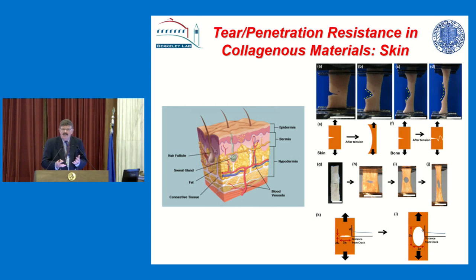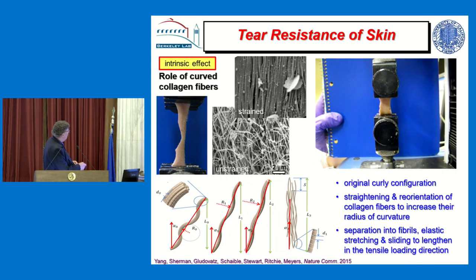Another one that's very interesting is skin. Skin is almost impossible to break. In fact, there's a hang glider in California that actually jumps off high buildings or in Yosemite with the wings attached to his skin. If you do it in the right way, it won't tear. And this is generally the so-called dermis layer. You can see how a piece of skin fails. It just tears open in a very, very elongated fashion. Doesn't break like bone. It's a picture of one here, and you'll see it takes forever to break.